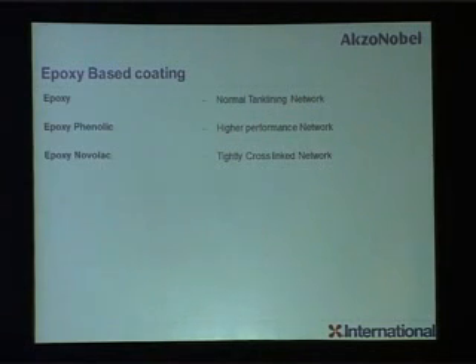Now, epoxy phenolic and epoxy novolac, the major difference between them is the crosslink, the functionality of the epoxy resins, and based on that functionality, you will get better crosslink densities. If you go for epoxy novolac, you will get better crosslink density. That means a better tightly crosslinked network, better resistance, better Tg. So it will have better chemical immersion resistance. It will have better temperature resistance.